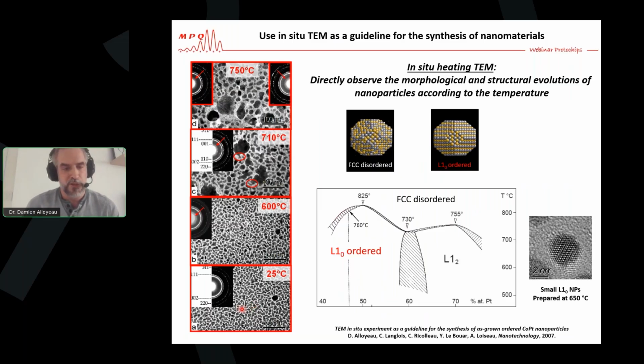And we were very surprised at the beginning of my PhD. We were fabricating those nanoparticles between 300 and 500 degrees. And we were very surprised because if you look at the bulk phase diagram of the cobalt platinum system, you see that at this temperature, the thermodynamic equilibrium of the system is this chemically ordered structure. But when you obtain the as-grown nanoparticles in this temperature range, they were always chemically disordered, so the high temperature FCC phase.